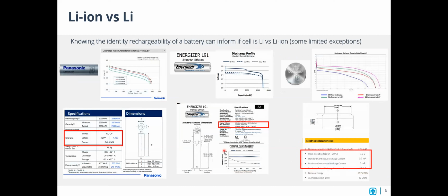So you can't always know whether you have lithium metal or graphite in your battery. Manufacturers won't always say, but if you have a cell, it's always a good idea to look at the spec sheet. And if you want to know if your lithium ion is rechargeable, just look and see if there's anything about charging in the specifications. If there is, that means you're dealing with a rechargeable system. Lithium metal batteries, typically single use again, will only talk about a discharge and a discharge current. There will be no mention of charging. And so if you don't see a mention of charging, these kinds of cells should never be recharged.